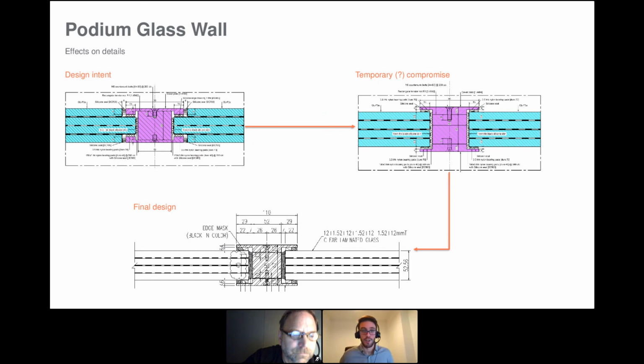So the most critical one was the detail between the rods and the glass panel. In our initial design intent, the idea was to have the glass recessed with the clamping plate of the rods being flush with the glass. As a compromise that we hoped was temporary at the time, we had to submit assuming that the glass was not recessed anymore, and therefore the clamping was sandwiching the glass panel together with the steel rods.